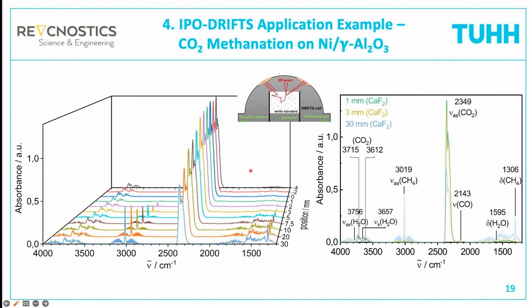And now I want to show you the spectra that we get. So here are the IR spectra that we measured when we fill the DRIFTS cell with the pure calcium fluoride. And these spectra are mainly dominated by the gas phase molecule. So we see here the asymmetric stretch vibration of CO2, and you can also see how the CO2 is converted as we go down the catalyst bed.